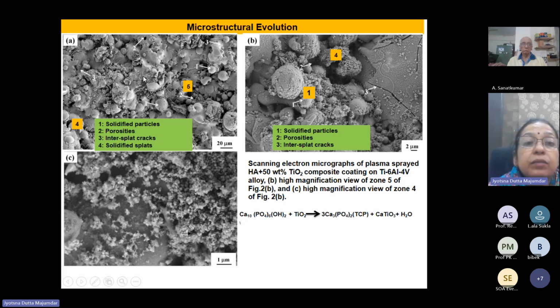So we find that this plasma spray deposition leads to development of a completely dense coating. Density wise it was 95 to 96%. Few porosities were there, and obviously at high magnification, if you see, you'll find some micro cracks are also present. This is the plasma sprayed 50% TiO2 composite coating, zone 4 and zone 5.